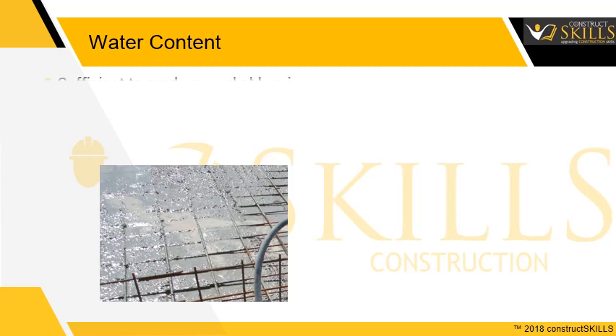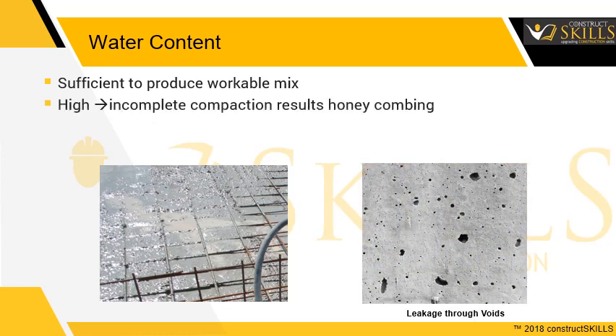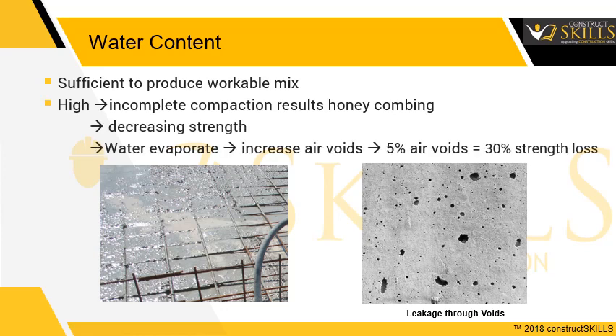Water content should be sufficient to produce a workable mix required for the particular method of compaction adopted. A high water cement ratio also leads to incomplete compaction. Upon evaporation of water from concrete, it leaves air voids. 5% air voids in concrete results in up to 30% loss in strength.